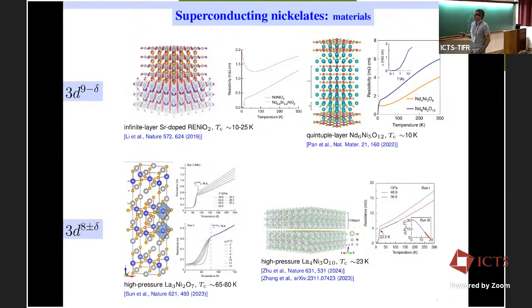And then last year there was the finding from the Chinese group of Meng Wang of a new kind of superconducting Nickelates, which are really high TC, going up to 80K at least as reported, but under high pressure. So there's always a caveat with these Nickelates: they have to be brought into thin films, or into some specific layering on a substrate, or in this case into a high pressure regime.